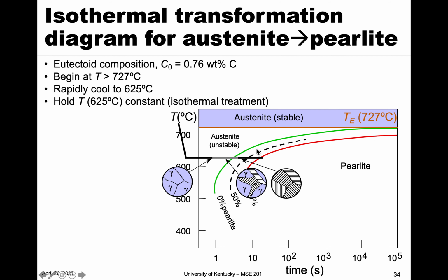All of these curves were put together from multiple different temperatures, running that isothermal experiment where we look at the Avrami curve for that temperature. So this is for the austenite to pearlite, and you'll notice that it stops here a little over 500.